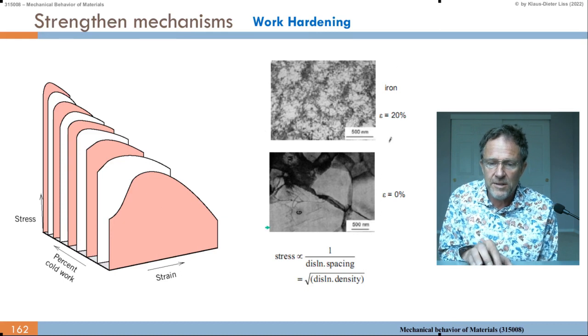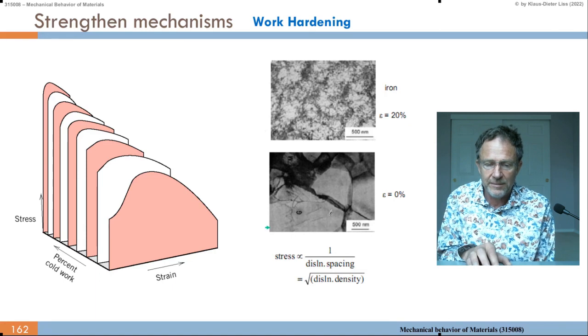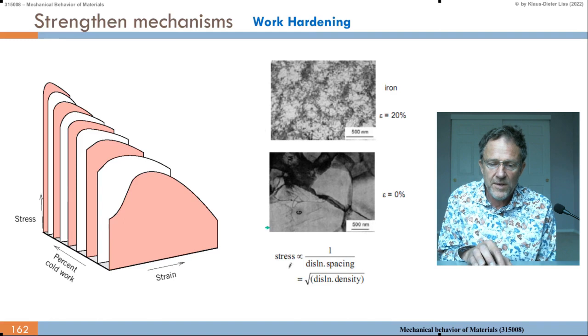Now here are microstructures of iron, which has been cold worked to 20%. So we see a lot of dislocations already inside there. At 0%, we see these big crystallites with a very small number of dislocations. There are always some dislocations in. So the stress which I can apply is proportional to 1 over dislocation spacing, which is proportional to the square root of the dislocation density.